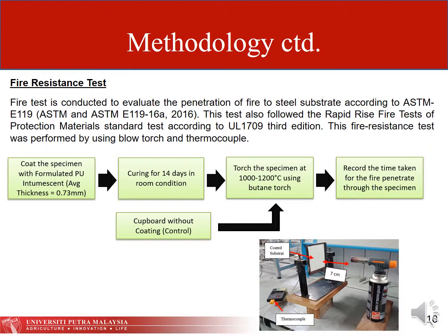First, coat the specimen with formulated PU intumescent. The average thickness of the coating is around 0.73 mm. It is cured for 14 days, and after that, torch the specimen using the butane torch and record the time taken for the fire to penetrate through the specimen. Repeat it using cardboard without coating as the control specimen.